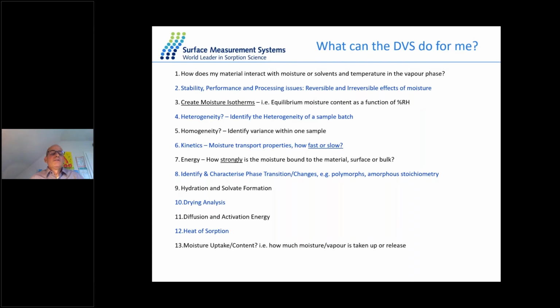You can measure the moisture content and moisture isotherm between 0 and 98%. That may change at high temperature, but we could cover the full humidity range, from dry 0.0% up to 98%. Identify the heterogeneity of a sample batch, or identify variance or inhomogeneity within one sample. With DVS, of course, you can follow the kinetics and measure the transport properties, meaning measure your sample at 1 point per second. You can do some measurements related to energy, measuring how strongly the moisture or other vapor is bound to the surface or the bulk of the material.